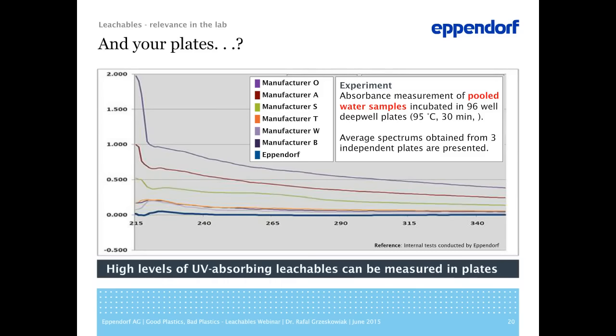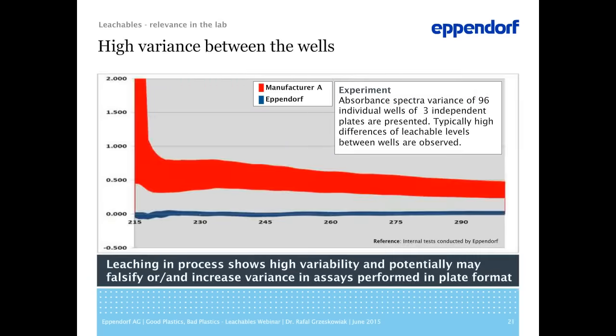As you see, most of the plates from different manufacturers tested showed quite high levels of UV absorbing leachables. This was pretty much consistent with our findings done with the tubes. We were not really much surprised. What was, however, very surprising is shown in the next slide, and this is the high variance between the wells.